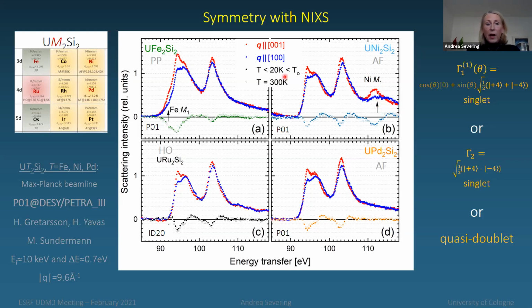We are now comparing it with the iron to silicon 2 sample. Also here in this polyparamagnet, we still see multiplets. And if you look at this energy range, it's again very much like the three other samples, only here it's different, but this is because here we are picking up the iron M1, which is underneath the uranium M5. But limiting the comparison to this part of the spectrum and comparing all these three other compounds, they have to say they all have the same ground state symmetry, which, as I've shown you before, is the gamma 1,1 singlet, the gamma 2 singlet, or we can't distinguish the quasi-duplet.